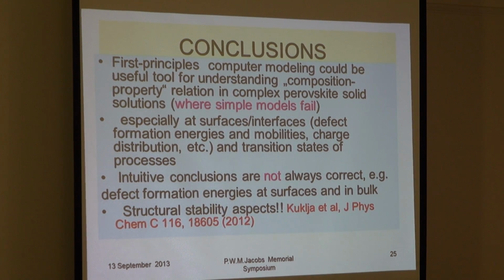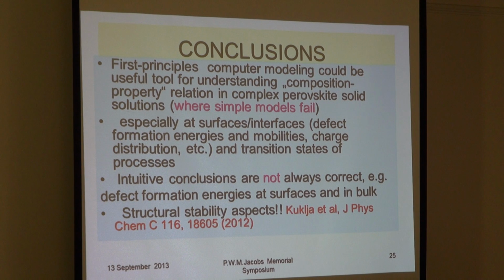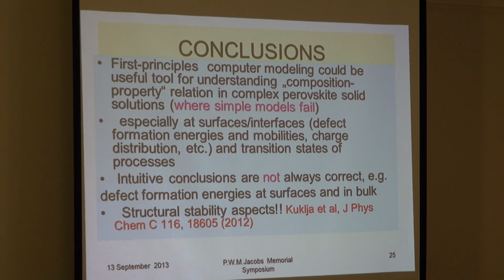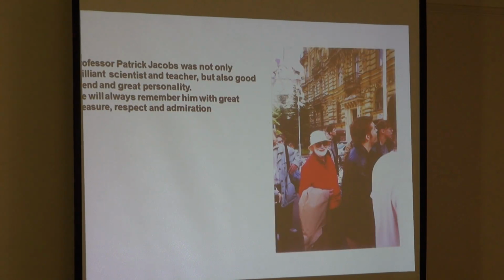So we understood that essentially there is, like in the Chinese symbol, yin and yang. Nothing is perfect, and when you have something very positive, it has at the same time some negative properties. So the fact that the structure contains such a high concentration of mobile vacancies turns into instability of this material. Right? There is essentially no solution, and there could be only a compromise, probably, between these two properties.